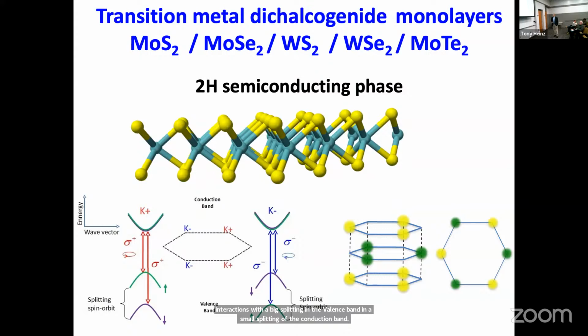Another interesting aspect of this, which I'm really not going to cover today, is that you have two degenerate valleys related by time reversal symmetry. And it was predicted and demonstrated early on that you actually have a very interesting possibility of selectively exciting one of the valleys or the other valley using the helicity of light. This is called valley circular dichroism. And that's an interesting aspect of these materials I won't be stressing today. So that's sort of a thumbnail sketch, zeroth order of the expected band structure of 2D materials.